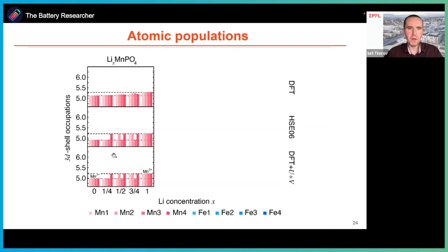And what we show on the y-axis is the occupation of the 3d shell of manganese, and on the x-axis, different lithium concentrations, and each bar represents one manganese ion in the cell. We have four of them. So we see, for example, that in DFT, the top panel, when we increase the concentration of lithium, the occupations of all manganese change simultaneously. This is so because the electron is delocalized and spread equally among all manganese atoms, which is wrong, of course.